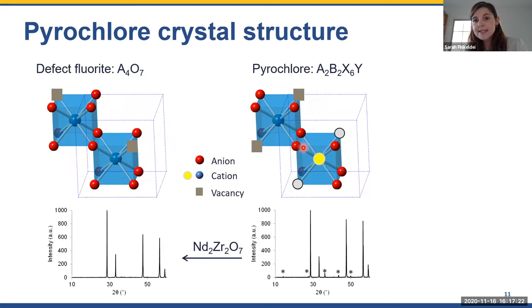And this is the A site. If you remember your chemistry class when you learned about sugars, we have the chair conformation. So think about all these X oxygens forming this chair where our cation sits in the middle. And then at the top and at the bottom, above and below this chair, we have two more oxygens, the so-called Y oxygens, which are at slightly shorter distances compared to the other oxygens. So this is a scalenohedron type environment, is how we would call that. And then we have the sixfold coordination of the B cation.